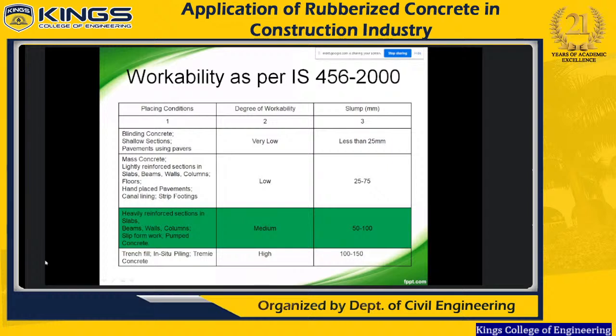Now tapered chimneys are also built, which we see in thermal power plants, where the diameter also changes. So it needs a suitable slump value. Most probably pumped concrete is used for such work, especially in silos, chimneys or high-rise apartments. We need pumped concrete, and slump should always be maintained at 100 or above, which is good for easy flow of the concrete.